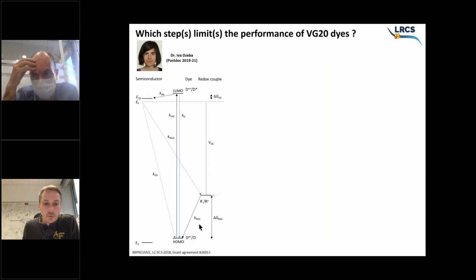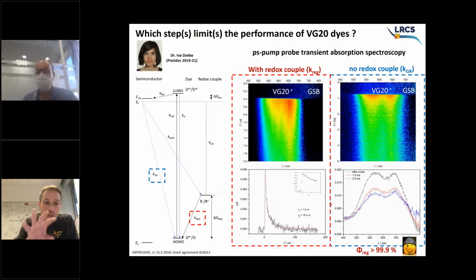You need to regenerate your dye, which is oxidized now. So you have the regeneration through the redox couple, but this kinetics also comes in competition with a non-wished process, that is the geminate recombination process, which means that the electron in titania recombines with the oxidized dye. This is something which can happen. And typically, to better understand those two processes, we use pump-probe transient absorption spectroscopy.